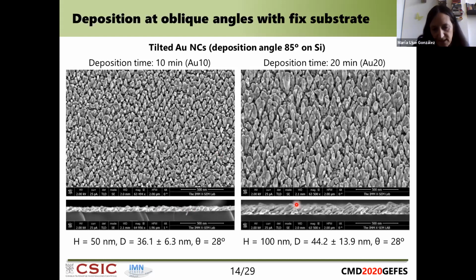So we fabricated two kinds of samples. One were samples where the nanocolumns were around 50 nanometers high and diameters around 36 nanometers, and others were longer. They were double, 100 nanometers nanocolumns. And then because the nanocolumns, when you grow them for more time, they also broaden in diameter.